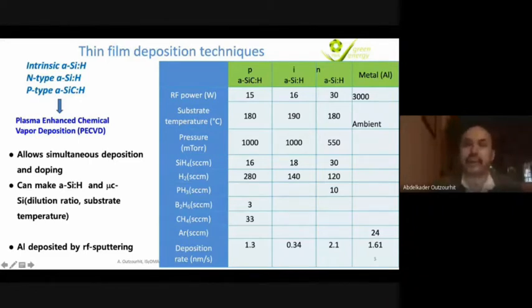Okay, for the N-type, as you can see, in addition to the silane and hydrogen gases, we also used phosphine for the N-type doping. And of course, the deposition rates are rather slow using this technique. They are on the order of 1.3 nanometers per second for the P-type layer, 0.34 for the intrinsic layer, 2.1 nanometers per second for the N-type layer, and 1.61 for the aluminum.